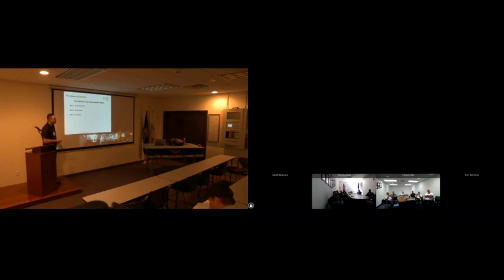Instances in litigation where someone's trying to sue someone else and they say, my system's failing, I'm going to sue the contractor, they put in faulty materials, and that's why I'm having an issue. We do a test called a metallographic test, which means we actually look down at the molecular level, at the granular level of the steel. We look for any defects. We look for any abnormal steel structure. We look for anything we can find.